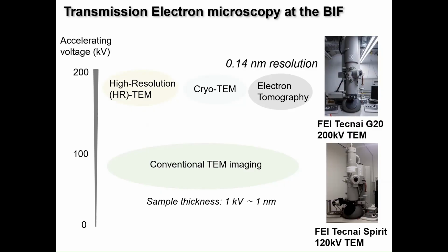So if you want to look at a small structure, nanoparticles, then we use 200 kV TEM to do high resolution imaging. And also with 200 kV TEM, we have capability of doing cryo-TEM and electron tomography. And the theoretical resolution of the 200 kV TEM is 0.14 nanometer. So I'm gonna talk about this conventional TEM imaging, and then move on to those specialized TEM applications.